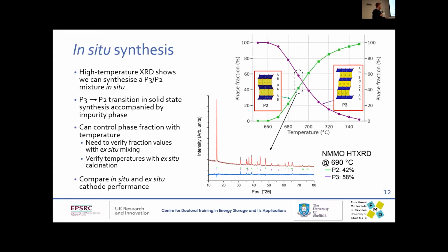So as you might expect, we've got this P3 to P2 transition. And at the midpoint, at roughly 690 degrees, which is as close as I could get, this is what it looks like. So slightly in favor of P3, but we're in the realms of about a one-to-one mixture. So what I need to do now is verify that this is the correct temperature, and that I can recreate this not using the high temperature XRD furnace, which I'm not sure exactly correlates to the furnaces we've got in the lab. And then second, I need to confirm that this ratio is correct.